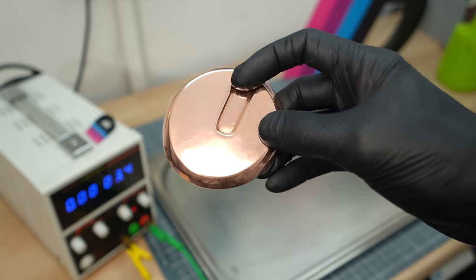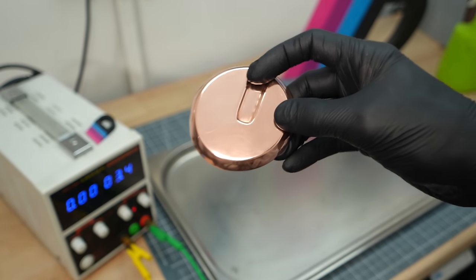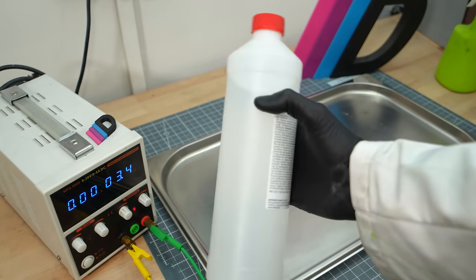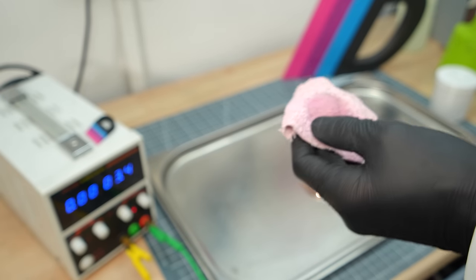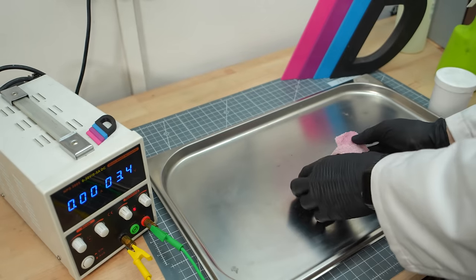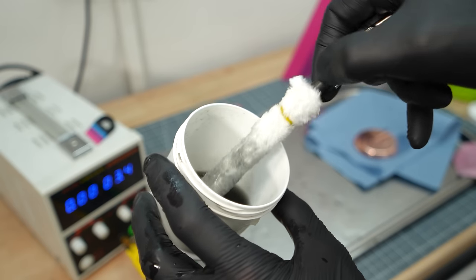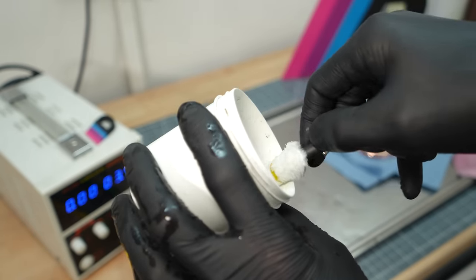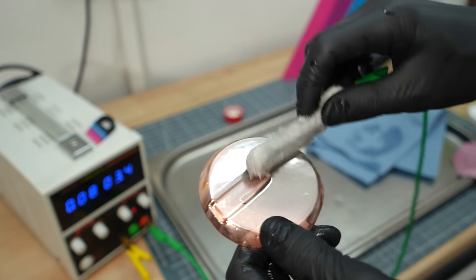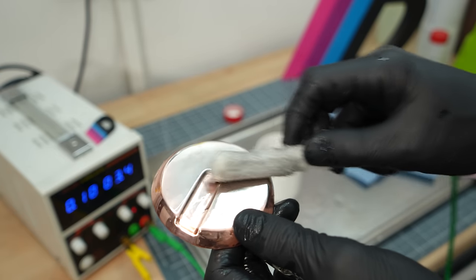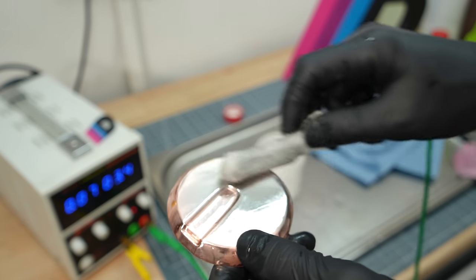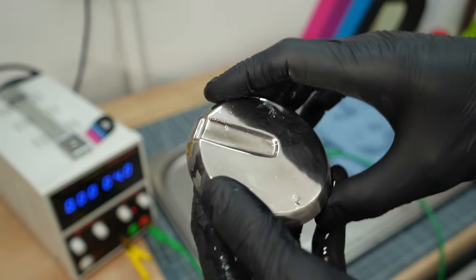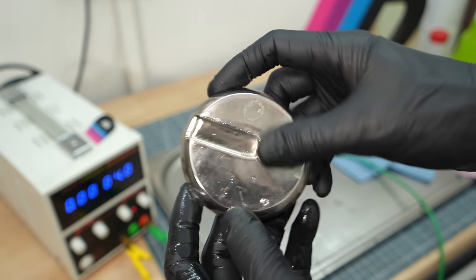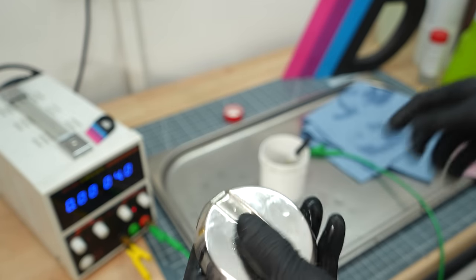Before starting to coat the parts, it is crucial that they are very clean. I use a galvanic degreaser for this. Either I degrease with electricity or I clean the surface thoroughly and rinse with distilled water. Then I immerse a graphite anode in the palladium electrolyte and circulate it regularly over the copper. The pen is connected to the positive pole and the 3D print is connected to the negative pole. Slowly, the electrolyte now deposits palladium onto the copper. Then I rinse well with distilled water and let it dry.